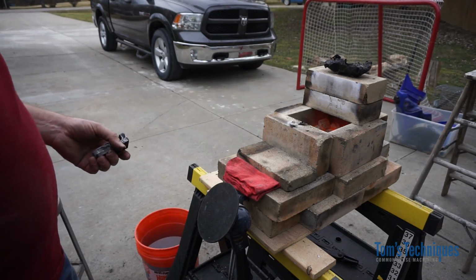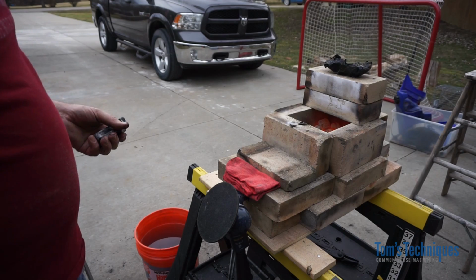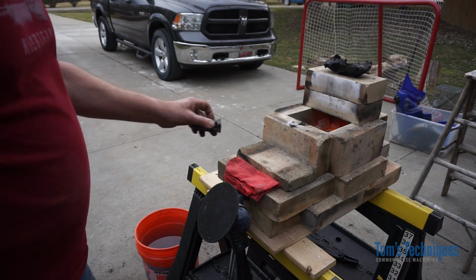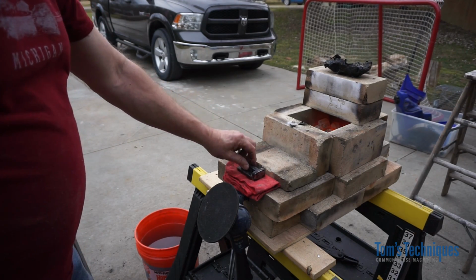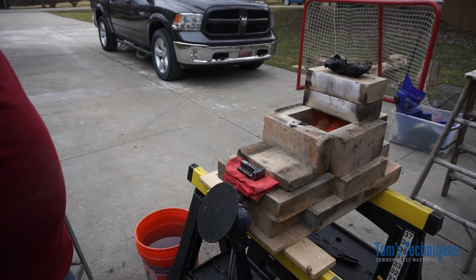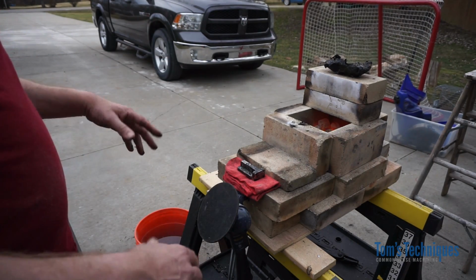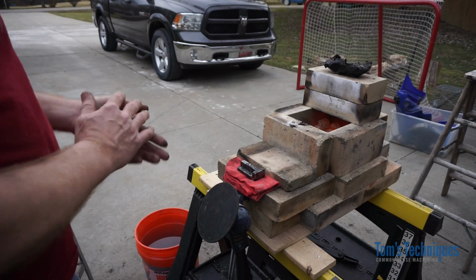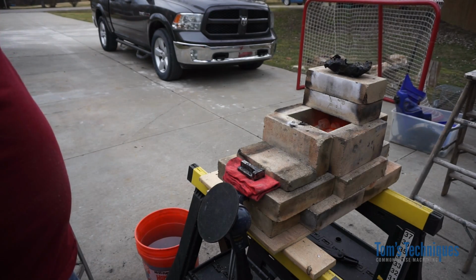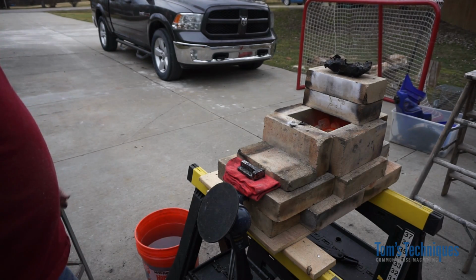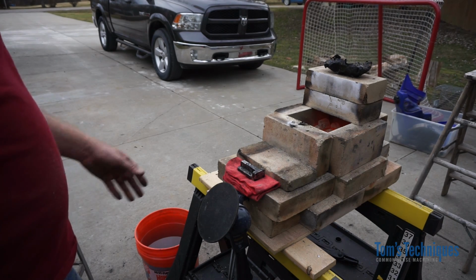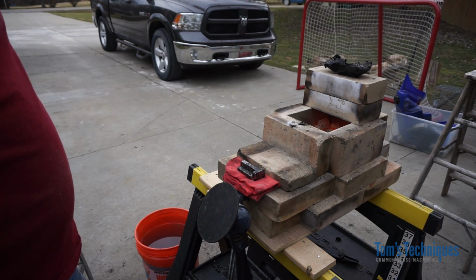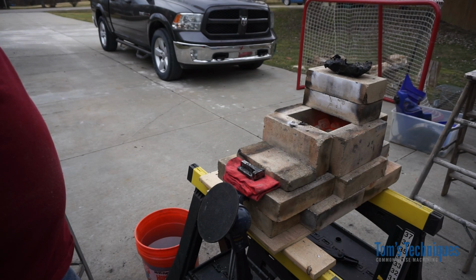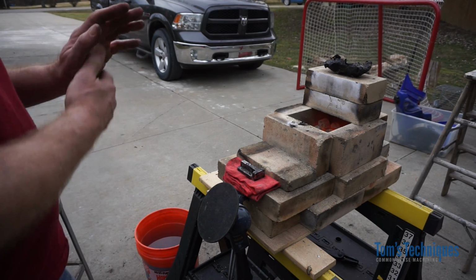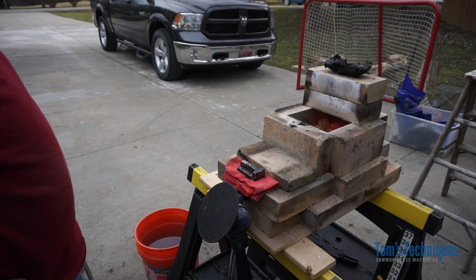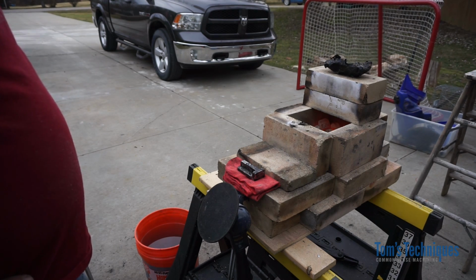Just to review a little bit, this took 3 batches of charcoal. The first one doesn't really do anything other than heat the furnace up, so you won't notice a whole lot going on. The second and third batches got nice and hot, so each one of those lasted about a half an hour, so we've got about an hour soak on this part. Should give it a nice deep hard surface on it. So that's about it.